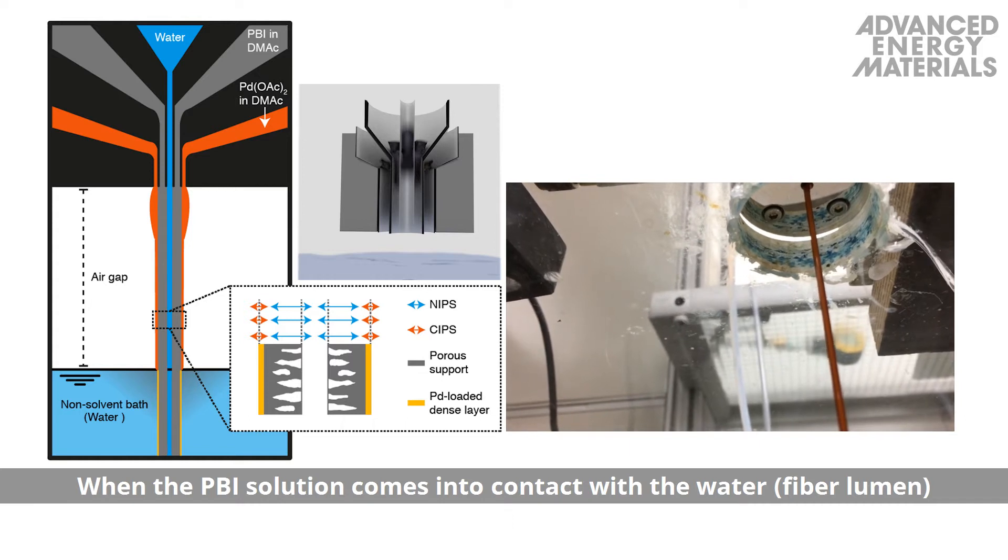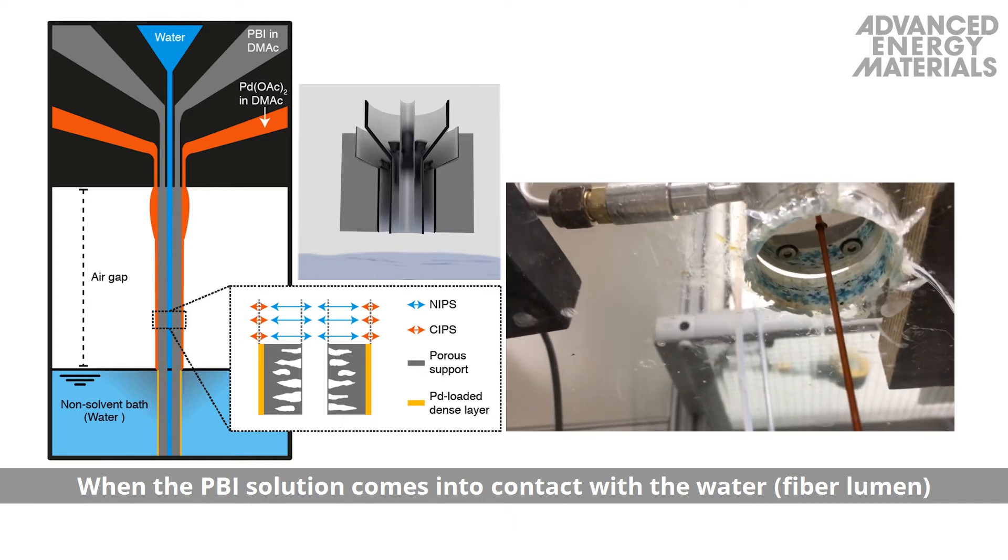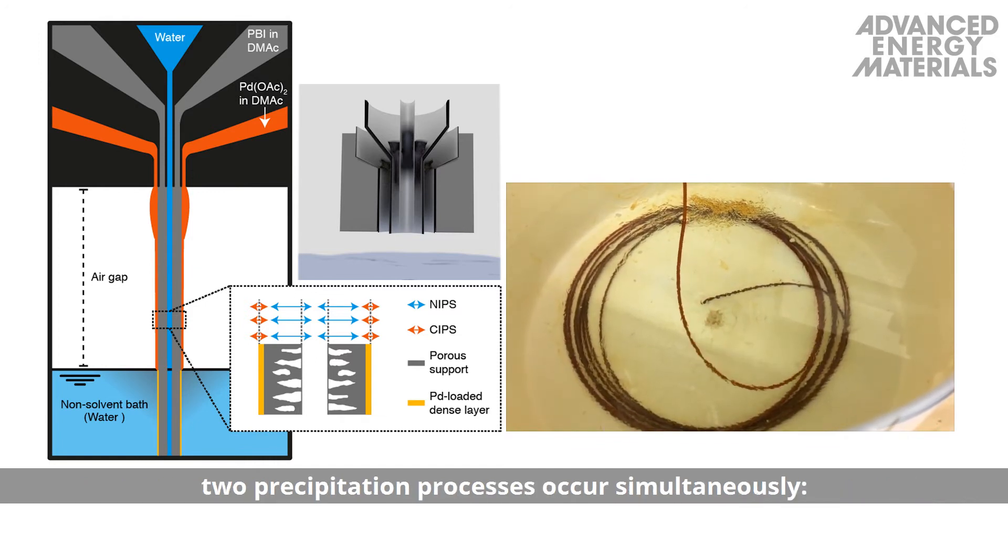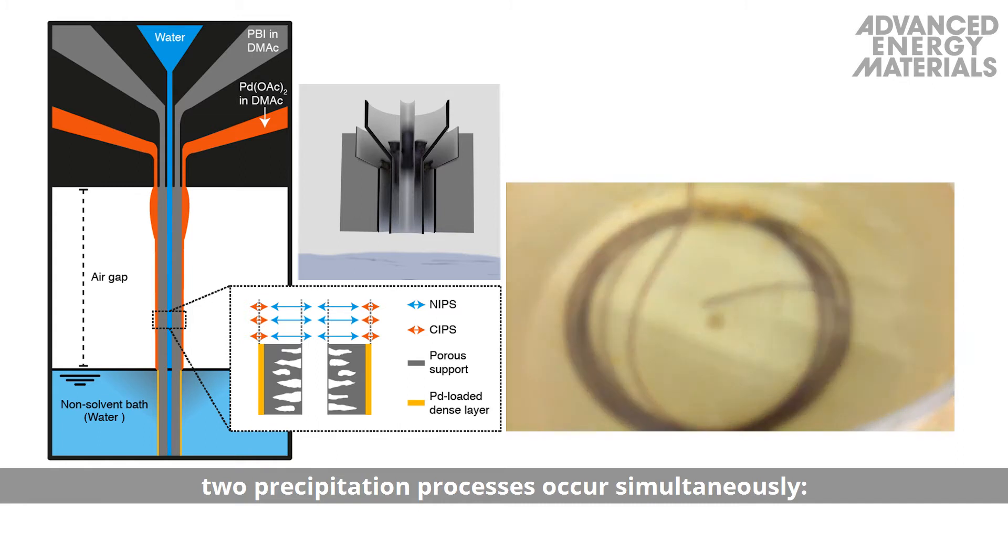When the PBI solution comes into contact with the water fiber lumen and the palladium-acetate dimethylacetamide solution fiber shell side, two precipitation processes occur simultaneously.